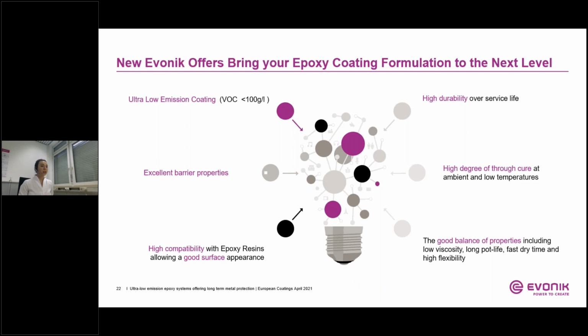Beyond very low viscosity with containing little or no plasticizer, the new curing agent show high compatibility with liquid epoxy resin, allowing a good surface appearance after curing. So, during the presentation, it has been also shown that due to the absence of non-reactive plasticizer, the coating is more thermally stable and will retain high performance during service life. This will extend the service life of structure and equipment, which additionally reduce their overall impact on environment.